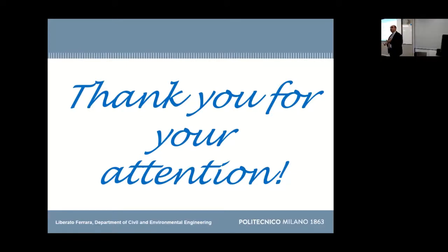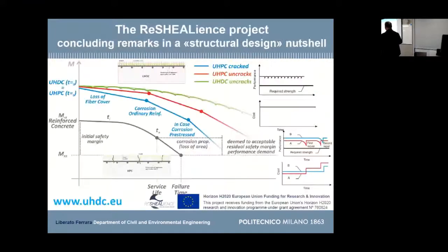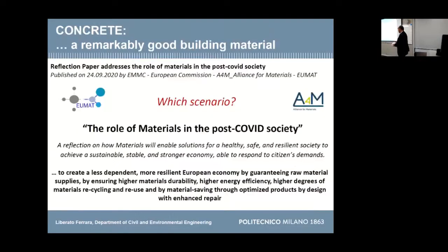So this means that at least we have tried to build up this diagram here. Obviously, the one you can see here is qualitative, but we worked to build similar diagrams for our structures. How do we build this curve? Well, you simply embed in your structural design equations a degradation model, for example, chloride penetration, sulfate erosion or carbonation penetration. As long as you have the progression of the aggressive front, you either remove it or modify your equation consistently. We ended up with numbers, and for this reason, immediately after that, I put higher material recycling, because you end up with service life of UHPC structures of more than 100 years, sometimes much longer.